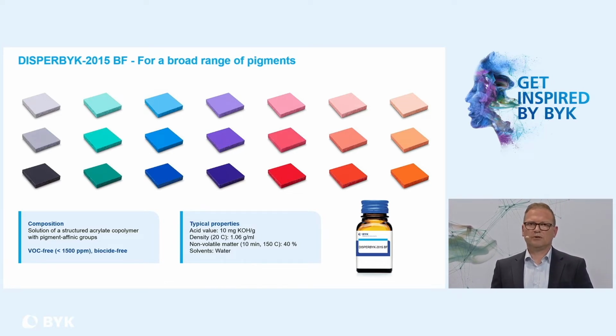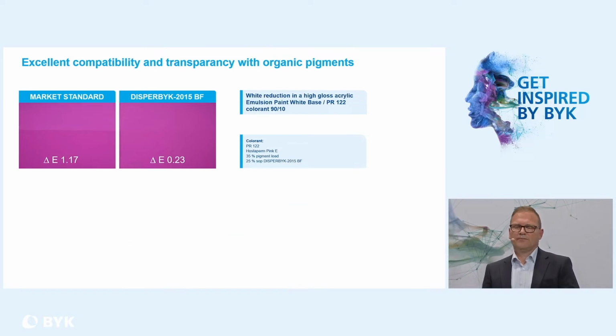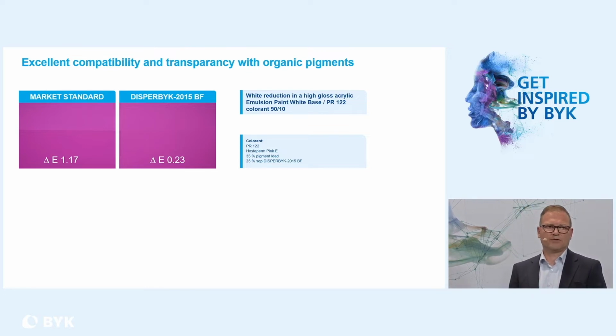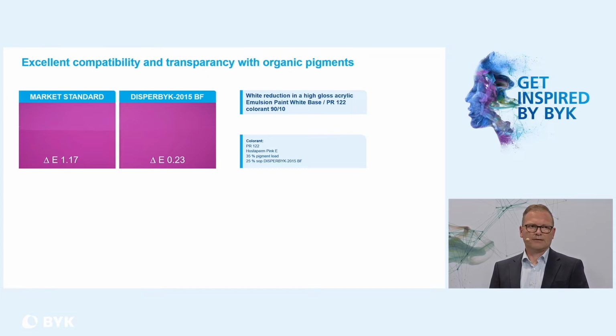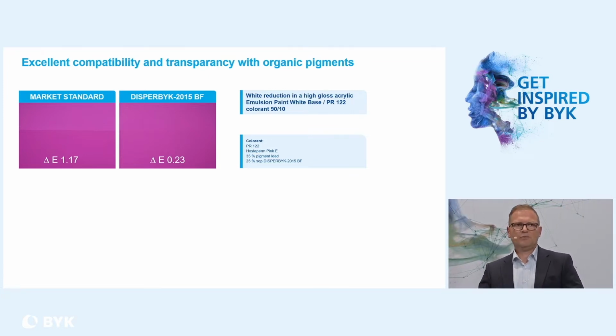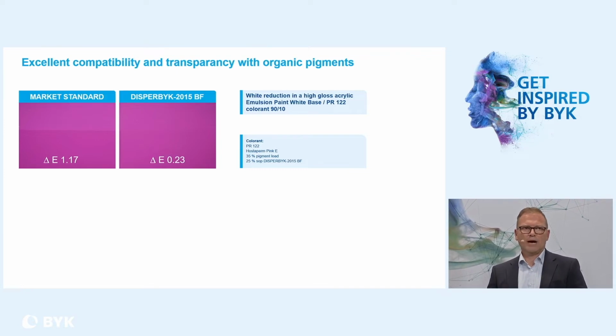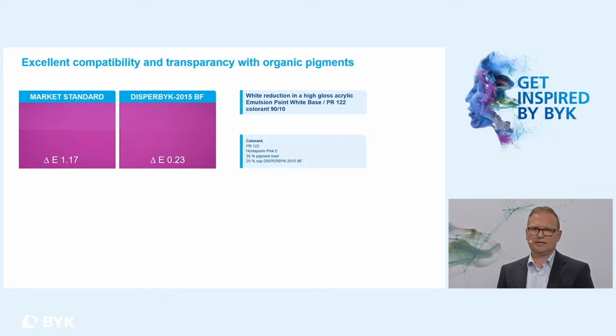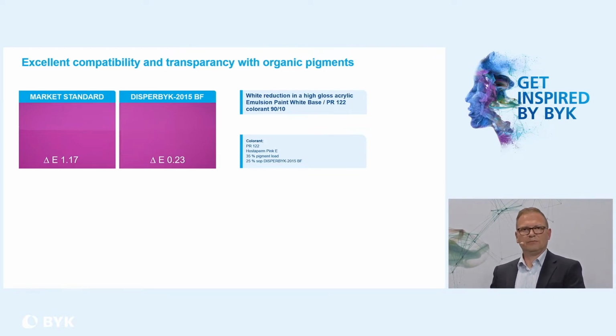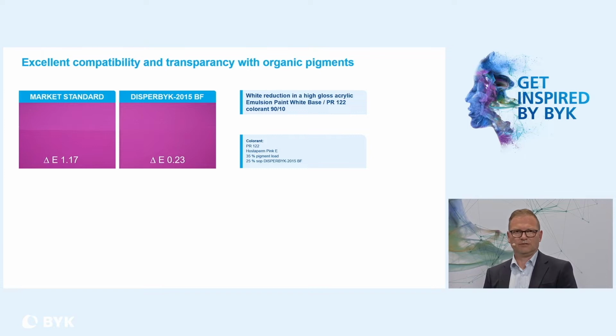And I show you now two examples. Here, first example, organic pigment, organic red, PR122. We prepared a pigment concentrate with 30% pigment loading and 25% solid on pigment of this BYK 2015 BF. And then we added this pigment concentrate to a white base paint, to a high gloss acrylic emulsion paint for wood coating applications. And you see the nice color strength development and the very low delta E value. So this BYK 2015 BF shows a very good compatibility to this system.